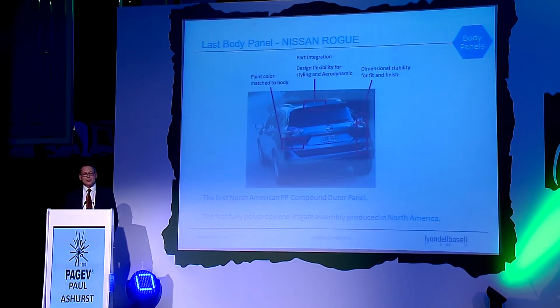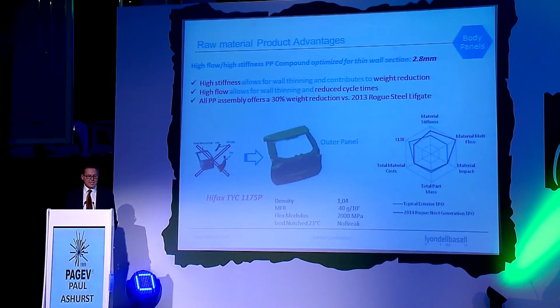This is the Nissan Rogue in North America. It won the Society of Plastics Engineer Award for innovation. This is the same car as the Nissan Qashqai in Europe, and this is the tailgate outer panel. It's the first fully polypropylene liftgate using our material. So this is not concept, this is not future, this is happening now. And the material, as we've seen before, gives a 30% weight saving. This material, again, is really high flow for thin walling. So it's MFR of 40, and it's got a flexural modulus of 2000.